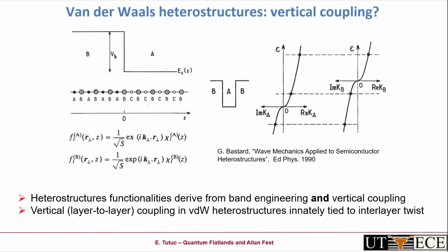So let me take a bit of a detour and talk about heterostructures. As an experimentalist, when I think about heterostructures, I'm used to drawing a band diagram with barriers and wells, and we use envelope functions to represent the states in a quantum well. If we look closely, the basis for this is that in a structure grown by molecular beam epitaxy, you have registration from one layer to another.